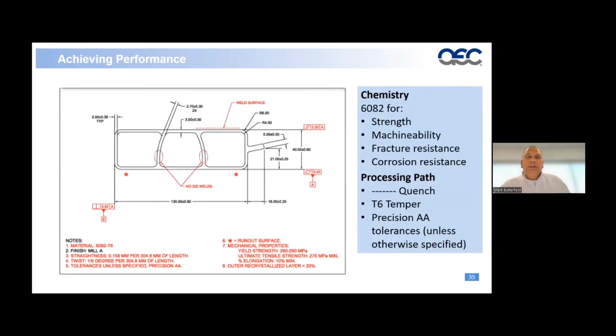So just some adjustments here. We specify the weld surface. We specify areas where there are no die welds. We put some controls on parallelism, flatness, and perpendicularity. We apply some twist and bow tolerances, make an adjustment in the alloy, and add a yield band. So for the 6082, we get some strength, machinability, and better fracture resistance. We get the fibrous grain structure, which helps our corrosion and fracture resistance. And then our processing path would be to quench, take it to a T6 temper, and utilize precision AA tolerances.